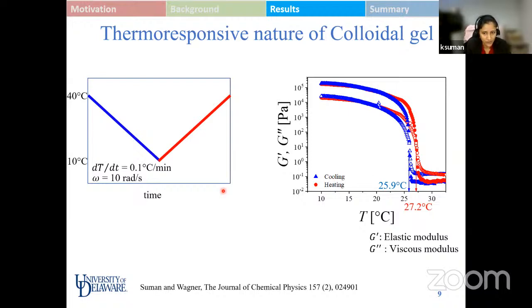So we take the sample, load it on the rheometer, and give it a very gradual change in temperature, as shown in the schematic on the left. We change the temperature gradually at a fixed ramp rate from 40 to 10 degrees, followed by reheating to the same temperature. So 40 degrees is basically the liquid-like state, and 10 degrees is supposed to be the arrested or soft solid-like state for this gel substance.